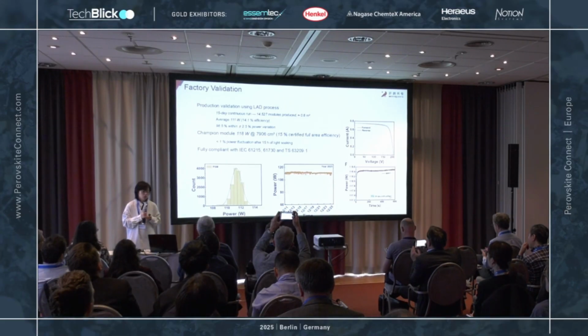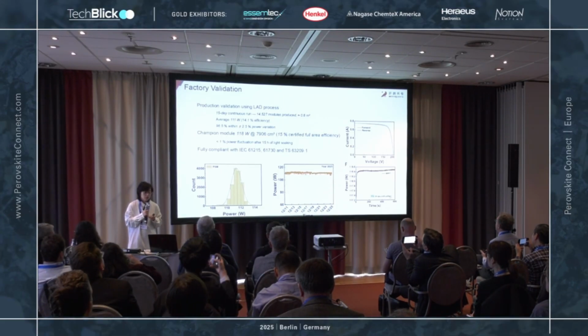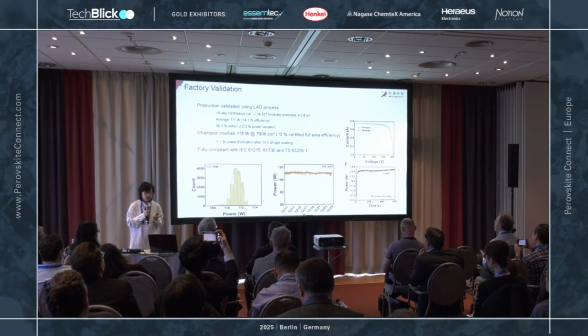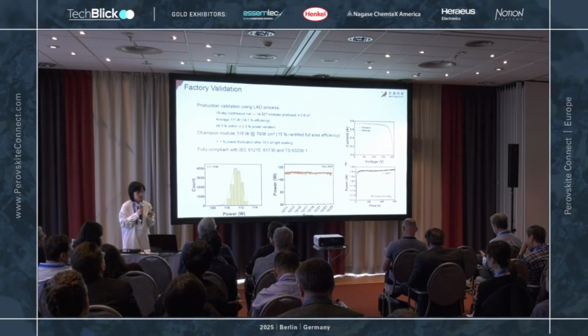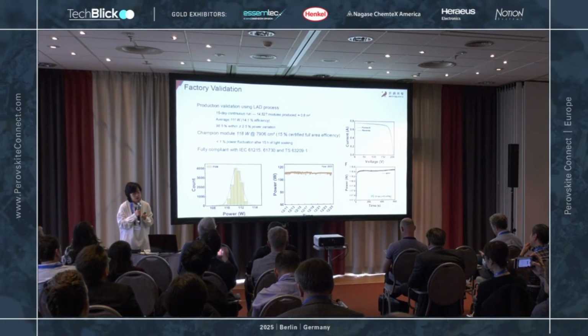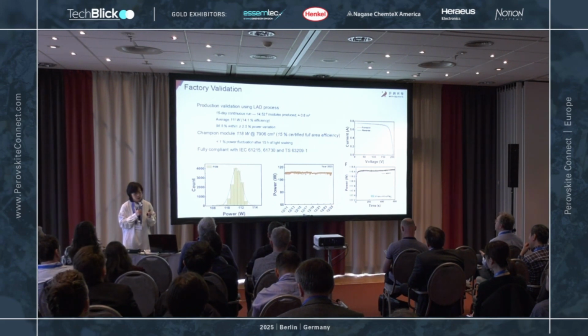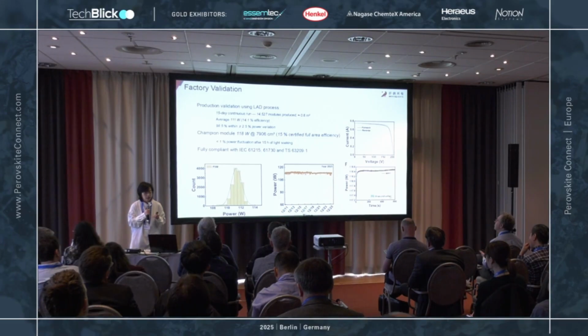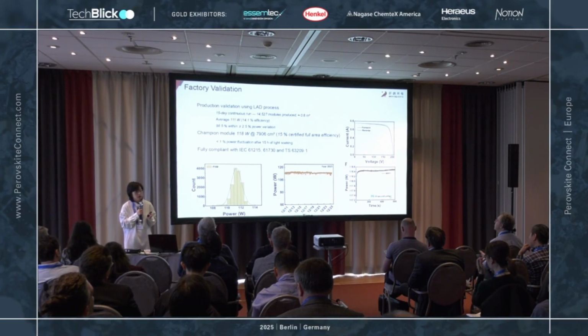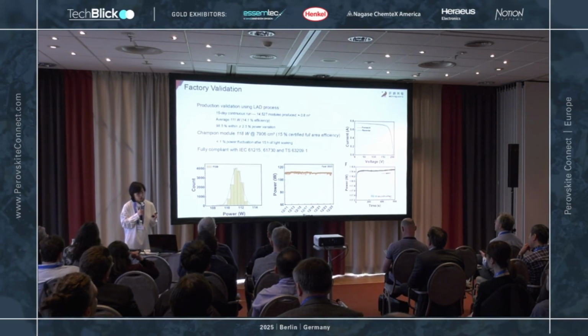Then we moved ahead with factory validation. We had a 15-day continuous run with average power of 111 watts, which equals 14% efficiency. And we found the lab process is very stable. 98.5% of the modules are within plus or minus 2.5% power variation range, and the champion module is 119 watts. All of the modules produced were fully compliant with the IEC test.